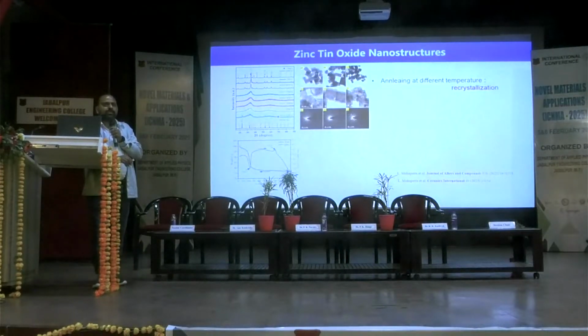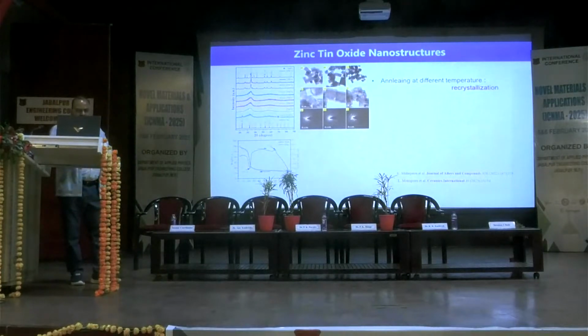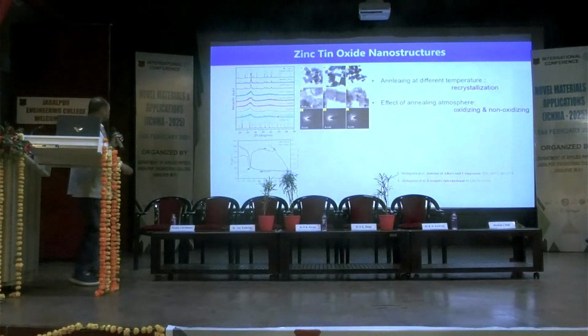If we change the surface, what is going to happen to the photoelectrochemical performance or the photosensitivity? That is the one tool which guides us to decide whether the material is good for this application or not. So here we simply performed heat treatment. We heated this material at various temperatures. You can see here, I think it's not visible at the back, but this bottom profile is the as-synthesized one. And if you see, we heated at 850 in normal air. What happened? You can see the profile change.